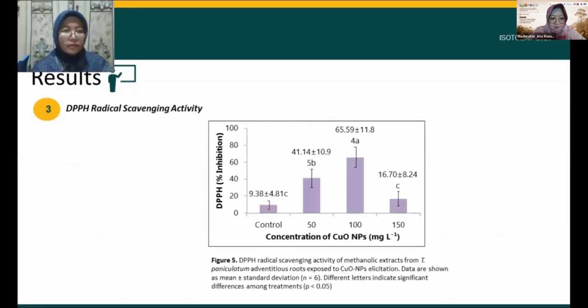3. Radical scavenging activity. Copper oxide nanoparticles significantly altered antioxidant capacity in adventitious cultures. Maximum scavenging activity was observed at 100 mg per liter, followed by 50 mg per liter, and both treatments showed pronounced enhancement relative to the control.